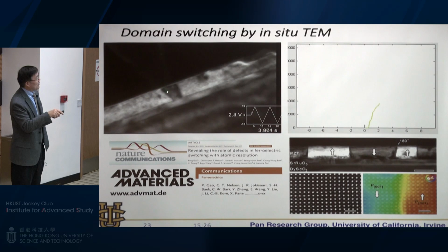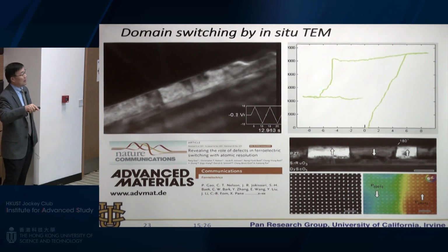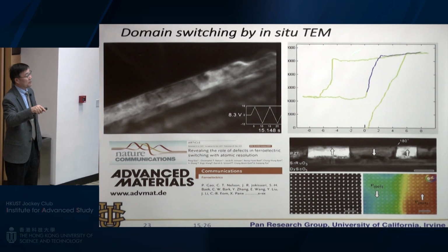You see the switching start from here and then go downwards and then expanding. The field decays quickly from center to the side. Therefore, they only switch in the middle part. Okay? And that is a hysteresis loop, typical for ferroelectric material.